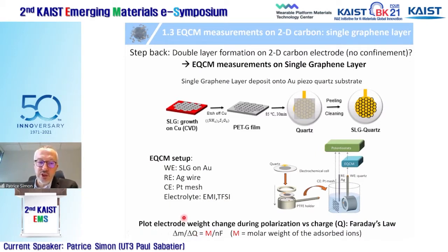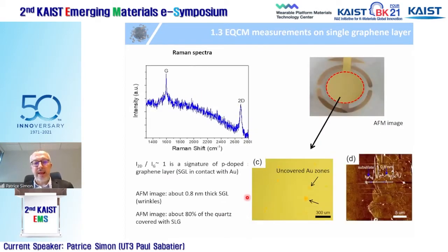And if you plot the weight change of the electrode from the frequency change versus the charge, you end up with a molar weight of the charge which is absorbed onto your electrode. And this is what we did.